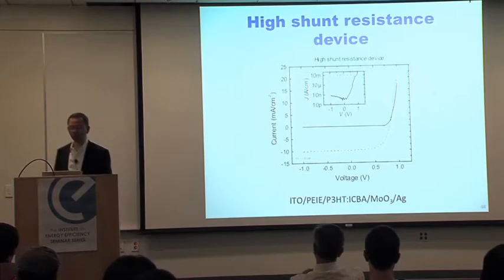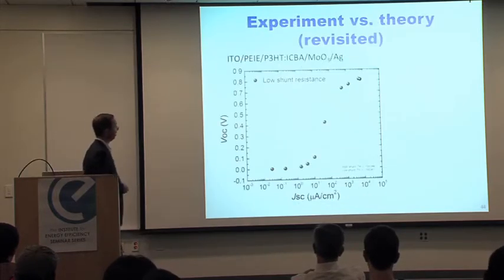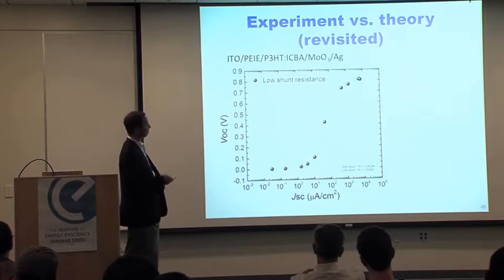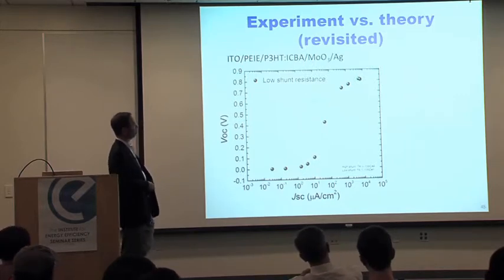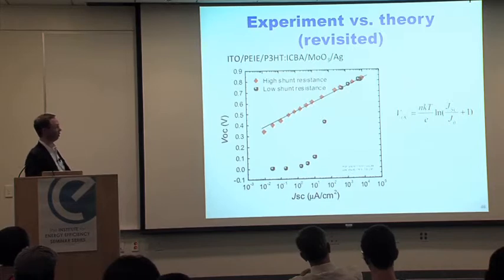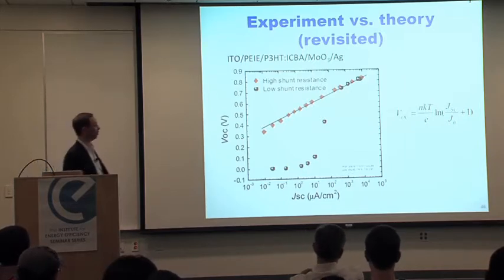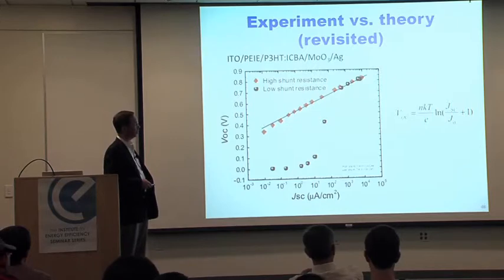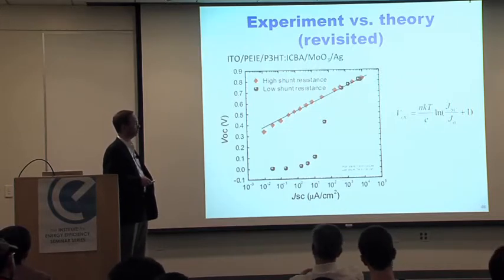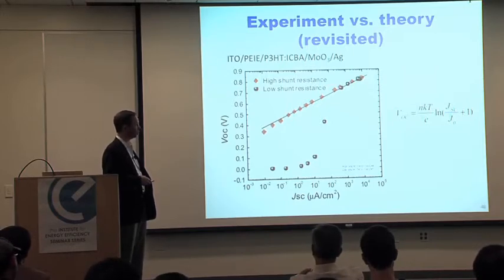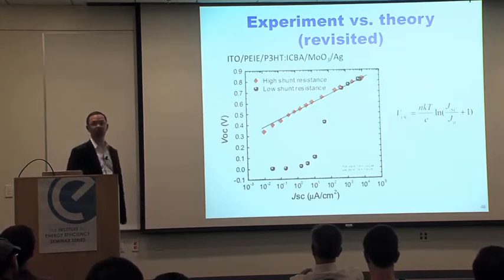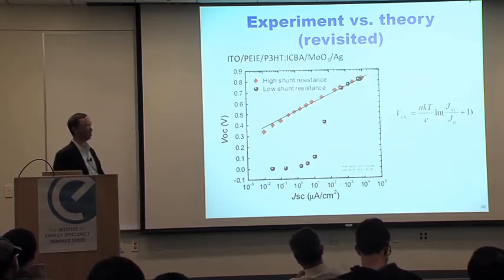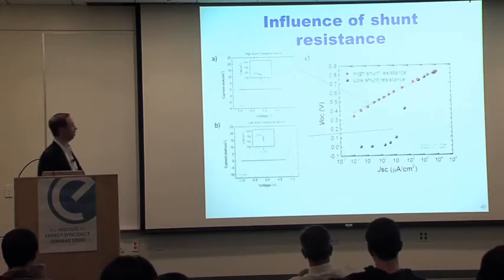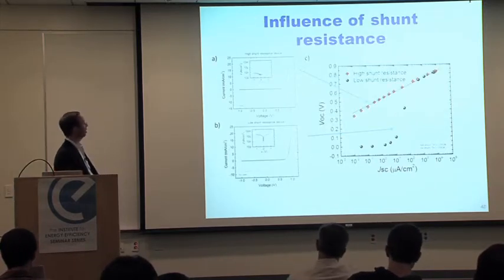Okay? And if you actually take a device like this, and now you do the same, you vary the intensity, and you measure the open circuit voltage, you get the red curve here. Okay? So now you can see that the voltage actually followed that simple Shockley diode relationship. This is just a Shockley diode inverted to express the VOC as a function of the current. Now it fits perfectly well. Okay? You see that it's actually consistent with what a Shockley model predicts, and this is just a summary of these different steps.